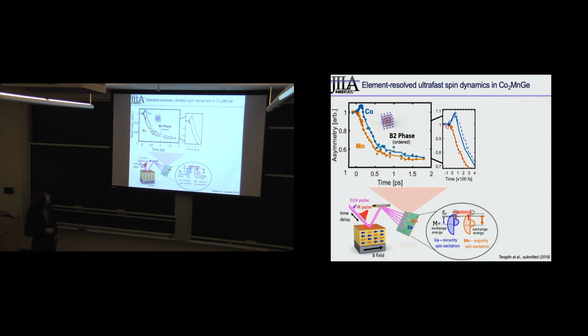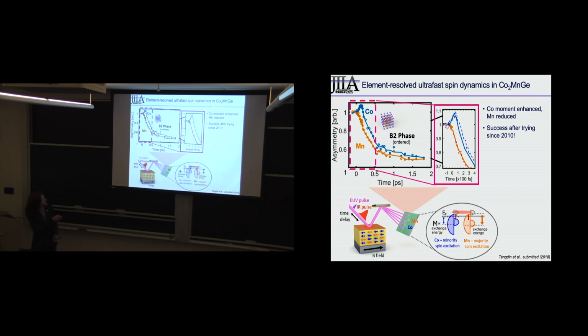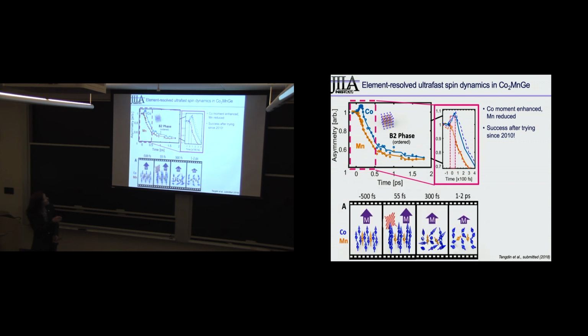Until we did the experiment, and it turns out it was even faster. Essentially immediately when we shone the laser light onto this Heusler alloy of cobalt, manganese, germanium, the magnetization in the cobalt went up, and in the manganese went down. So in this alloy, you get some transfer of spin polarization from the cobalt to the manganese, and then after you shine light on it, you get a transfer back extremely fast. So it was the opposite of what we expected.